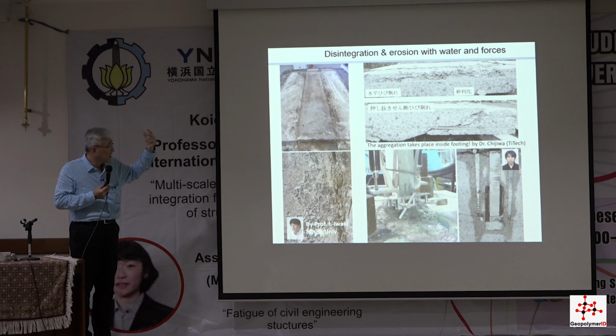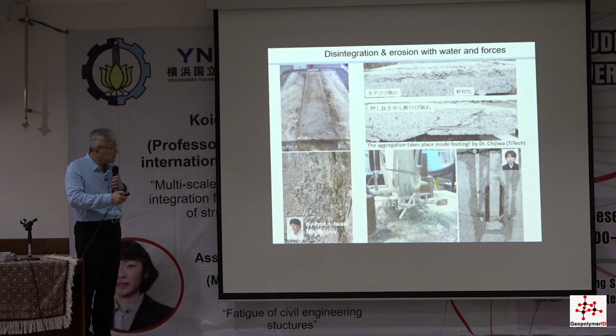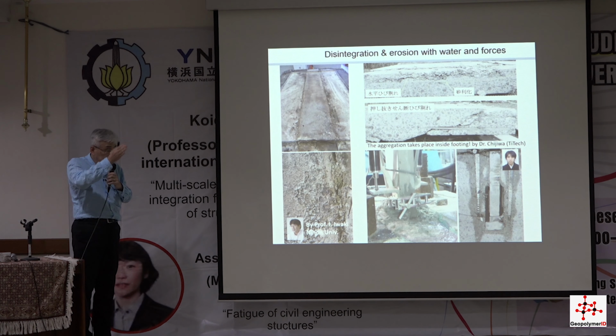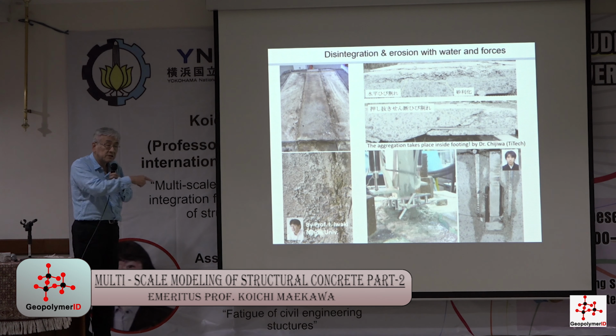Nothing happens. But he put some stagnant water on these footings. Under these cycles, water can come inside, between the face of the steel plates and concrete. In this case, maybe around 1,000 or 2,000 cycles, it happens.